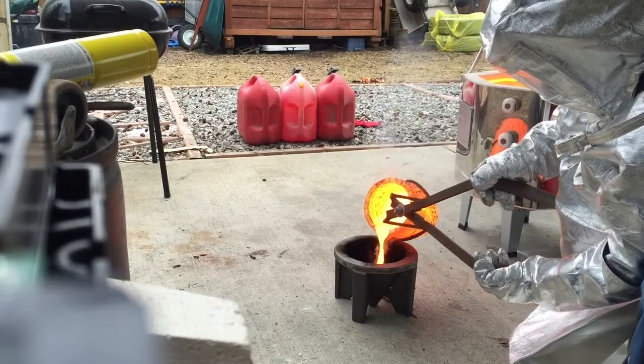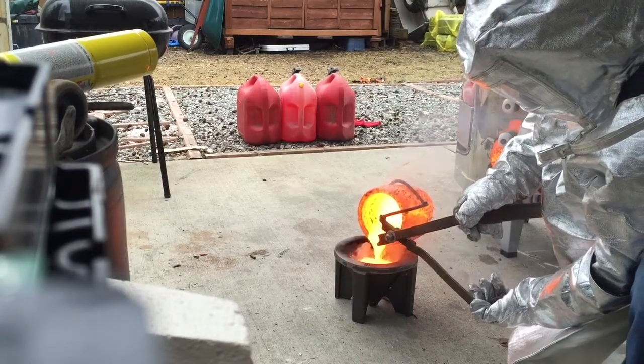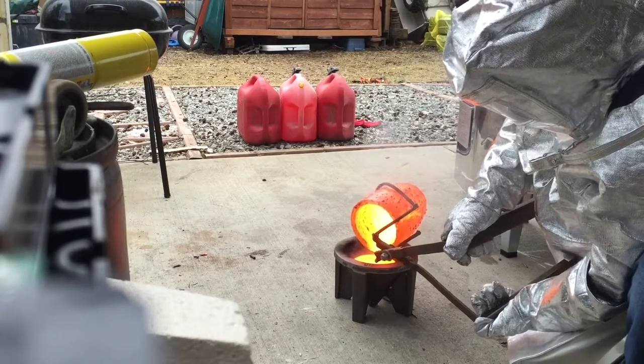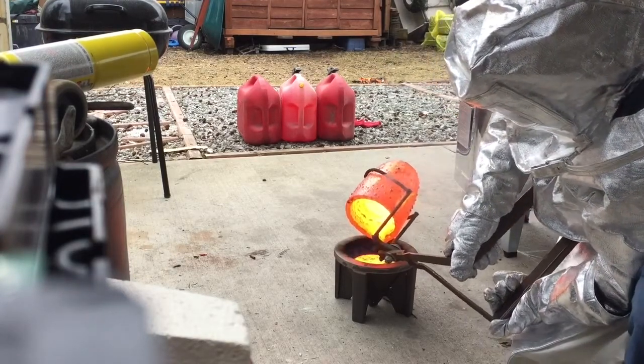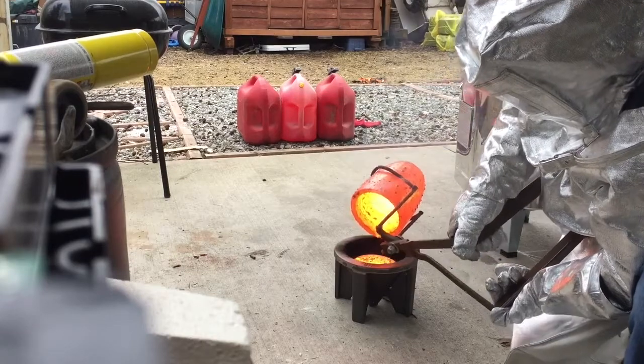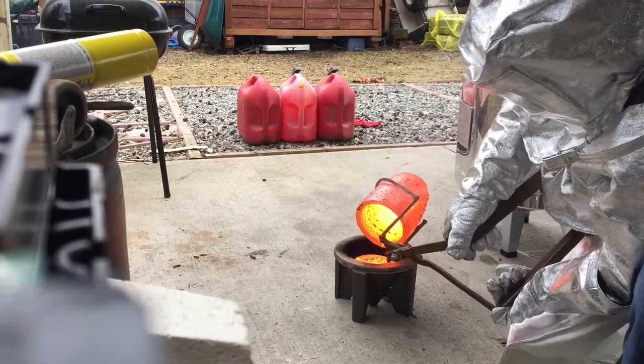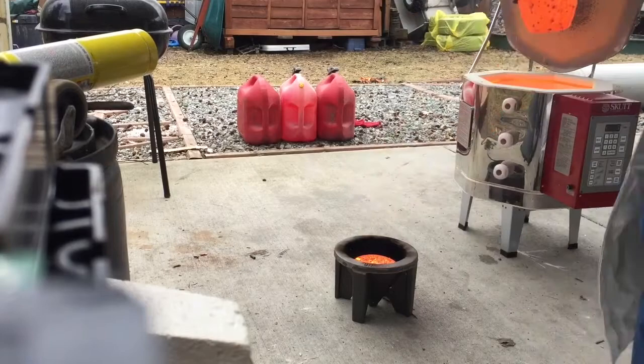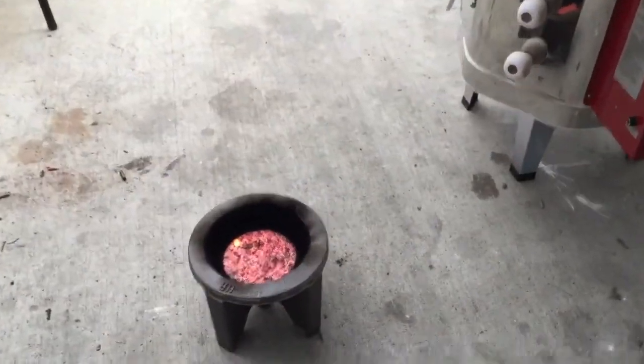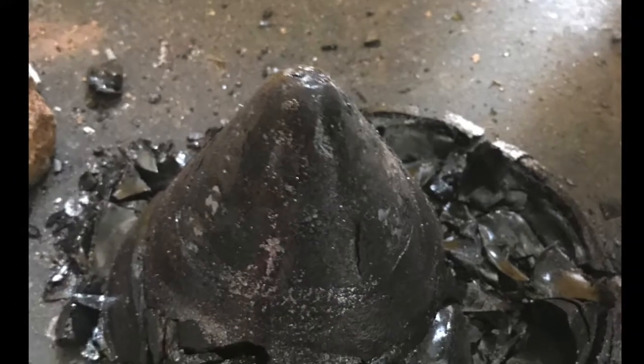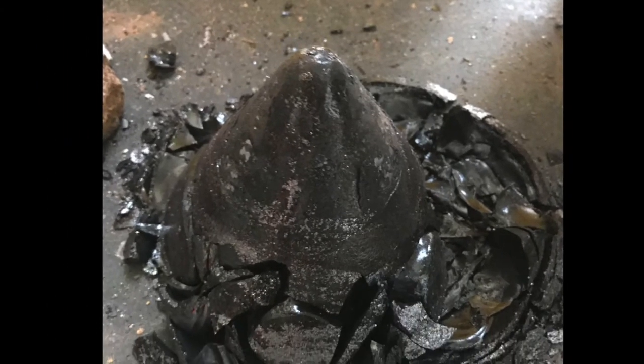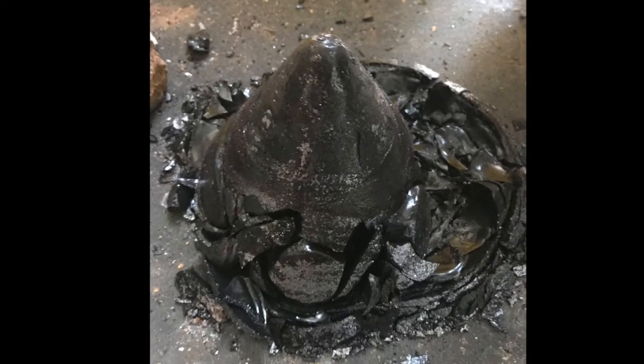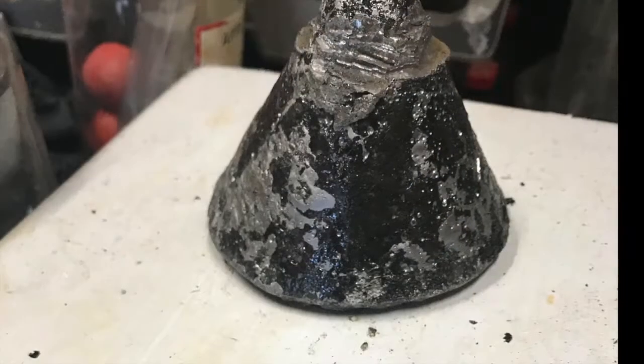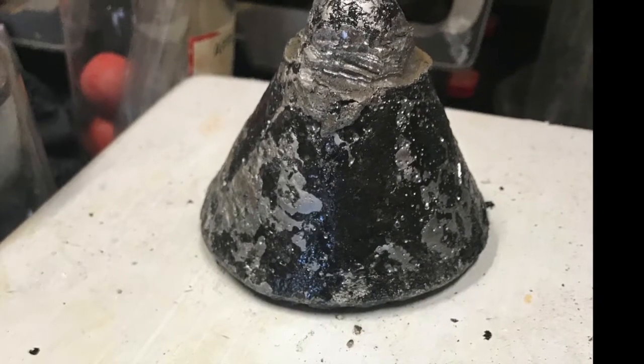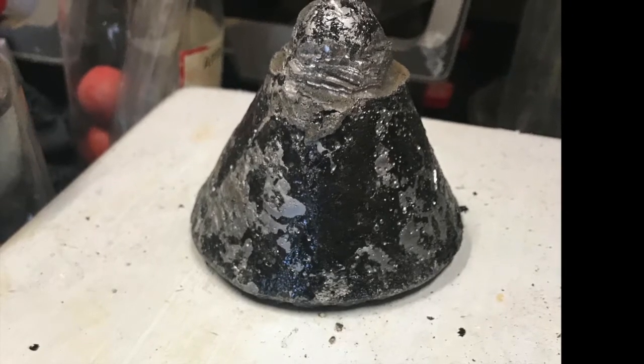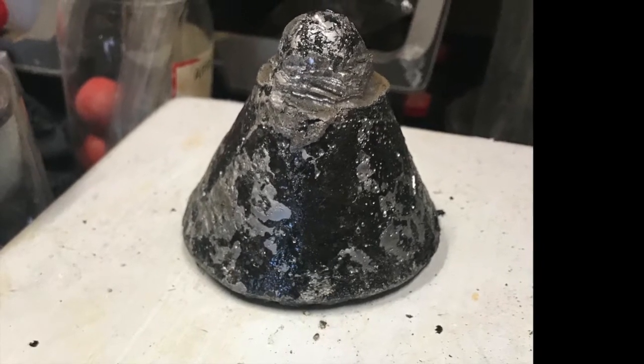What was needed was a precise recipe that is tailored to the material. A flux was made up, and then the concentrate smelted at 2,000 degrees. If the recipe's right, then the precious metals will report to the lead prill or cone at the bottom of the cone mold, and all the other junk will report to the slag. This is the lead cone at the bottom of the slag, and we call it a prill.